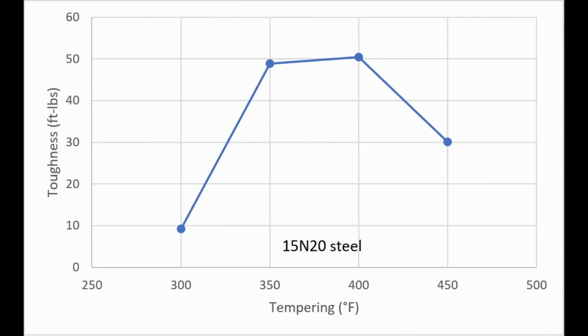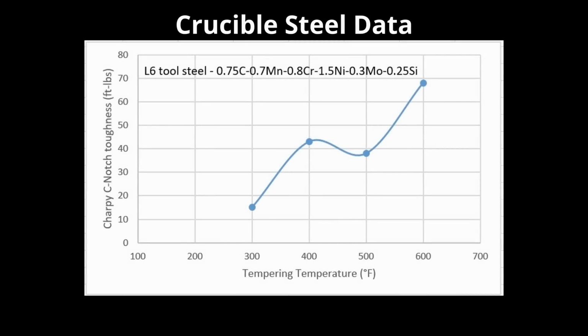Now the toughness, I saw a huge increase in toughness by going from 300 degree temper to 350. So 300 degree temper was just under 10 foot-pounds. Going to 350 degrees got to almost 50, and then 400 degree temper bumped it up a little bit. And then tempering at 450, there was again a drop in toughness. This is from a phenomenon called tempered martensite embrittlement. So this is somewhat unexpected because usually the softer steel is, the tougher it is. So we temper it hotter, it gets softer, and we expect the toughness to continue to rise. But instead, it went down by tempering at 450.